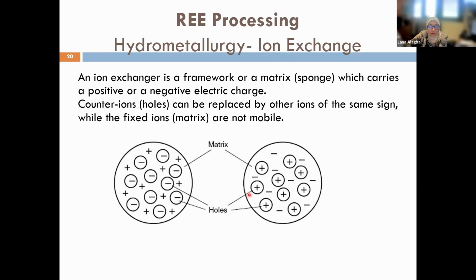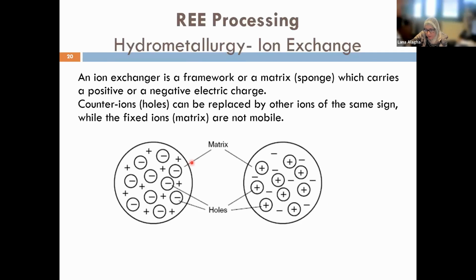Now, of course, these exchangeable ions can be modified using materials engineering. You can have whatever functional group you want, depending on the metal that you want to separate, to improve selectivity. It is a good processing technique in the case of a very low concentration of ions in solution. So it is mainly used for water purification. It was used actually in rare earth solution purification, but after the development of the solvent extraction process, solvent extraction became more common than this type of technique.